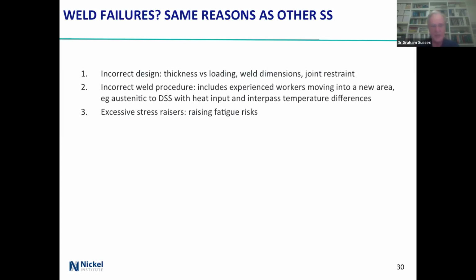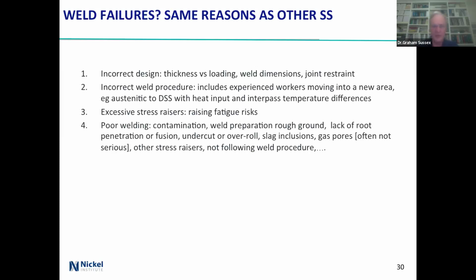Excessive stress raisers, well, that's all over the place because you raise the fatigue risks. Poor welding, contamination, rough ground surfaces, lack of root penetration or fusion. That never happens, does it? The welding's always good. Undercut, overroll, slag inclusions, gas pores. Got to say, people worry about gas pores all over the place, but unless they're due to water and you wind up with a whole cluster of them, then it's usually not too serious. And other stress raisers, just not following the weld procedures.